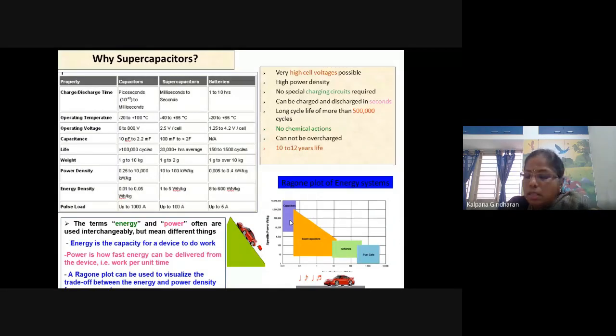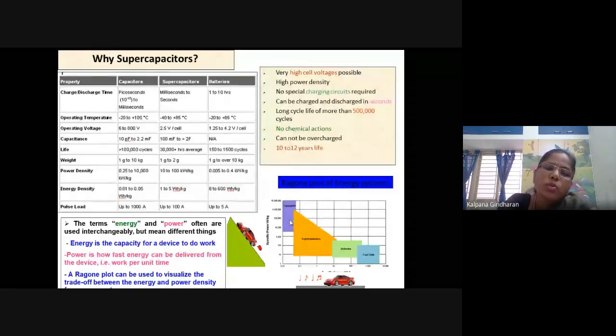Since the EDLC doesn't have any chemical reactions involved, no Faradaic reactions involved, the life of a supercapacitor is more than a lakh cycles, whereas for batteries it is 150 to 1500 cycles. Even the weight, when you use carbon material, would be around 1 gram to 2 grams, whereas for batteries we know we generally have heavy metals.